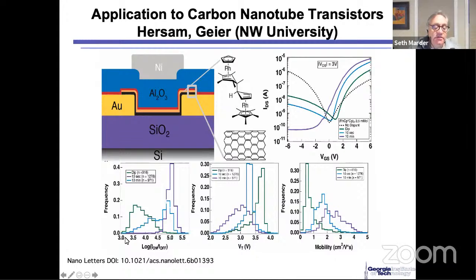And so what happened is they end up making N-channel transistors. They end up getting something with a pretty good on-off ratio. These are basically histograms of the frequency of the number of devices. And you can see here they made 1,200 devices, and they end up getting this histogram of the performance. They show that they get a relatively low threshold voltage. And in this work, they end up getting mobilities. Now, these are N-channel mobilities on the order of maybe 2 or 3 centimeters squared per volt second.